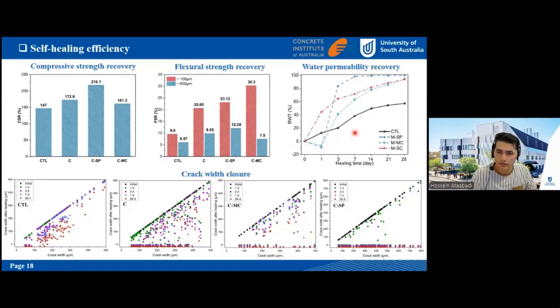In terms of the water permeability or water ingress recovery, the maximum recovery we could achieve by the control sample was around 47% after 28 days, while we achieved this amount even in around 3 days with the samples that had the capsule installed. So it shows that our capsules are really fast responsive. They react very fast, and they can heal the cracks very fast.